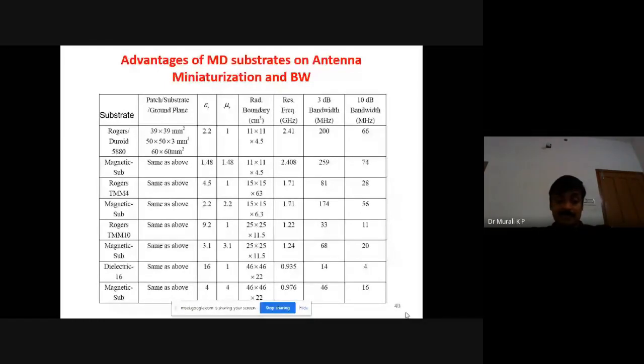Like if you compare the last 2 rows, if you take a dielectric substrate 16, having dielectric constant 16, so it's epsilon r and mu r, you can see 16 and 1, because it's a dielectric, so mu r is 1. Whereas the same thing, if you take a magnetodielectric substrate having 4 and 4, 4 epsilon r and 4 mu r, you will get the same miniaturization.